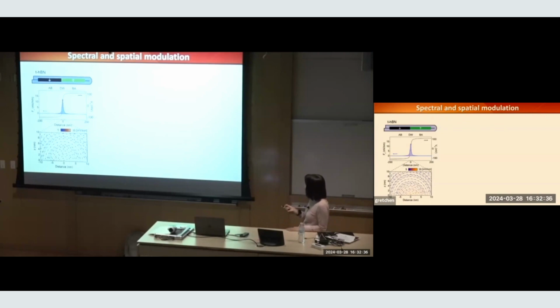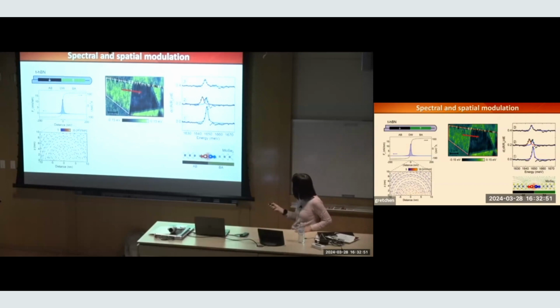So in a large domain, I've shown you the potential is actually flat, right? Within a large domain, the potential is flat. But between two adjacent domains, there's a quickly changing in-plane electrical field. That in-plane electrical field can actually induce an exciton Stark shift because it's pulling the electron and hole in different directions.